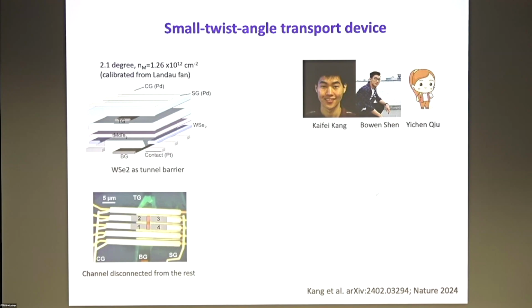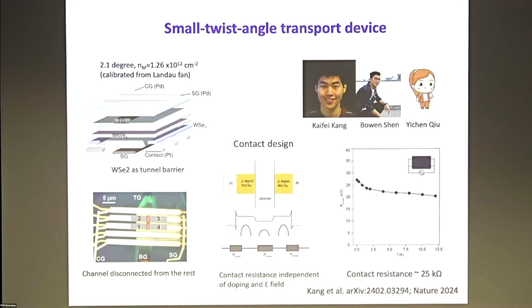It has 4 contacts that work, and the rest of the device is actually disconnected unintentionally from this region that has uniform moiré region. What we usually find out, for those who care a little bit about the details, is that if you have a uniform moiré region that separates from the region with no moiré, typically the channel just breaks there. Maybe it's just cracks or something that happens. But we have a 4-terminal device here.